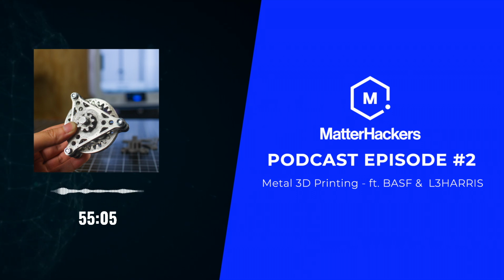I have turned one part into two parts accidentally by removing it off the print bed. Yeah, it's a good thing about the filament, but it can be bad depending on how you look at it. But it's actually really easy to deal with after you've printed. It's fairly soft, malleable, so easy to clean up with a little X-Acto blade or sanding. So you can get that part really smooth and exactly the way you want it before you send it off for debinding and sintering. But because of that, it's also not that difficult to break if you're removing the part from the bed. You can snap a part or break a feature off if you're not careful.